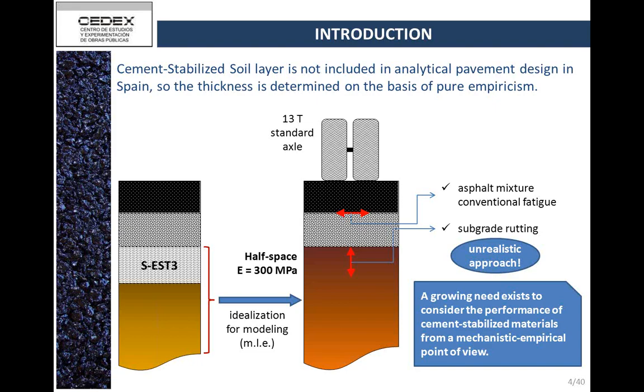As I said, we have a catalog, and sometimes we also do analytical design, and the catalog has an analytical design procedure behind it. This is the typical idealization that we use in order to design these types of pavement. What we typically do is join these two layers, the cement stabilized layer and the soil layer, and use a single layer. So we model the subgrade like a half space, and we assign a 300 megapascal modulus. Then we compute the typical analytical design. We compute asphalt strain and vertical strain at the top of the subgrade, and then we apply a fatigue load. It is a matter of fact that this approach is quite unrealistic. We actually know that the performance of the subgrade is going to be very good, so we never worry about the performance of this type of subgrade.